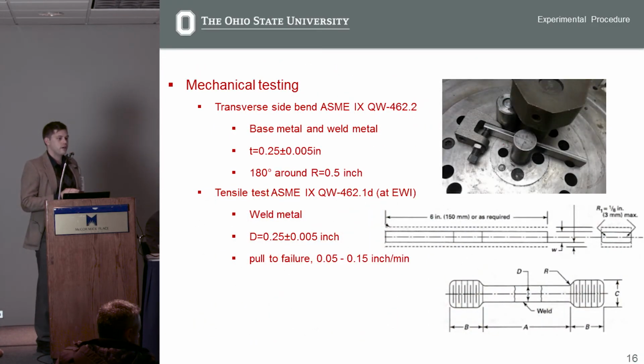After we made our nice overlay mock-up, we cut it up into samples that were intended for mechanical testing. Transverse side bending experiments were performed to test the strength of the fusion boundary and the weld metal itself. And also, tensile tests were performed to analyze the mechanical response of the weld metal alone. And those were performed at the parameters on screen.